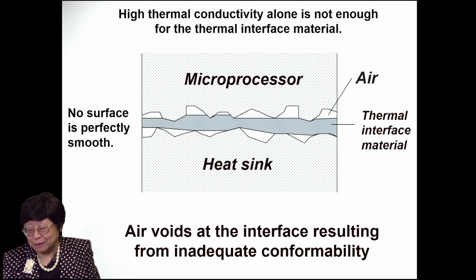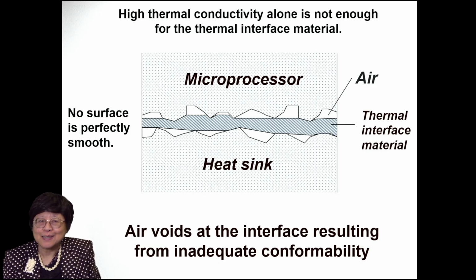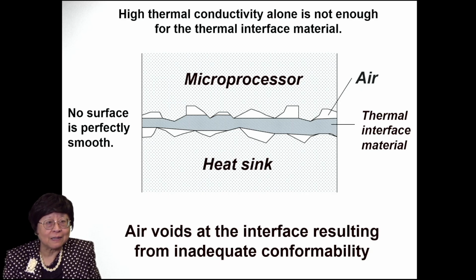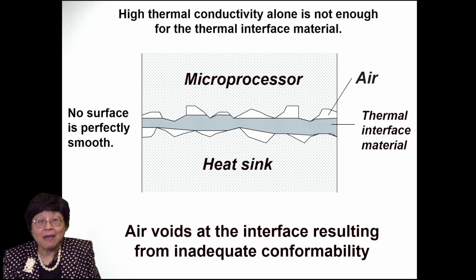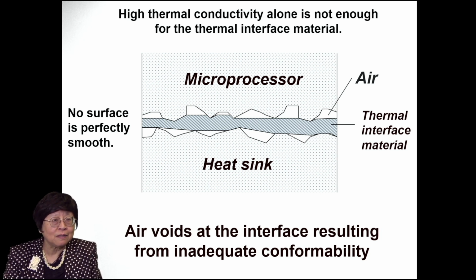Now, all along, people have been assuming that high thermal conductivity is the criterion governing the performance of a thermal interface material. But I figured out that it is not the criterion. There's another criterion which is just as important. And that is because no surface is perfectly smooth. So there are microscopic ups and downs, and air resides in those microscopic valleys, and air is a thermal insulator.